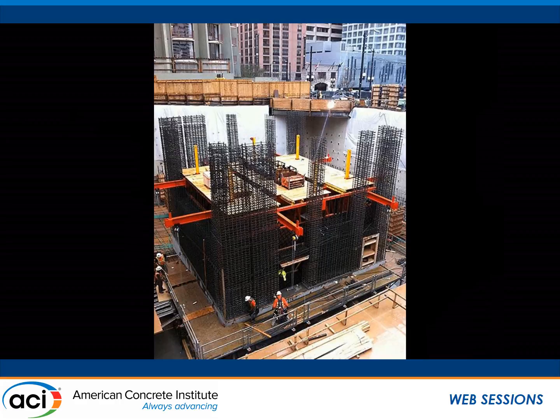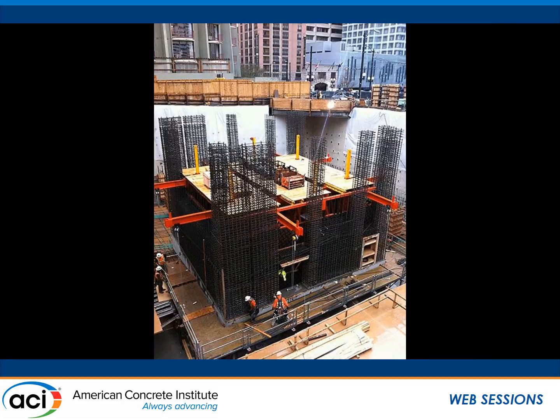On the core walls, you can see now the core is coming out of the ground. Not sure if you can see this, but we had to basically increase the ductility of these cores quite a bit, so we put tie steel throughout the base of the building because this is where most of the forces happen and most of the rotation actually happens, and you want to make sure you have confinement of the concrete throughout. We specified a 1/2-inch gravel because there's a lot of congestion, as you can see.